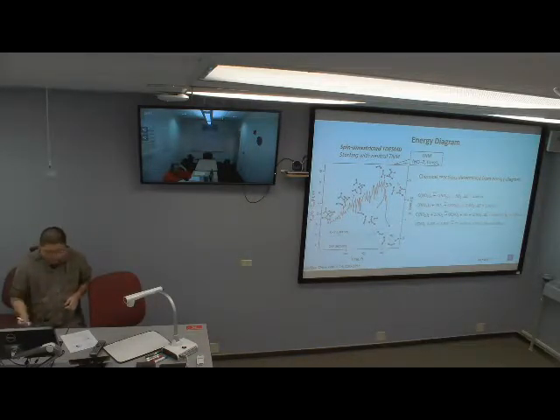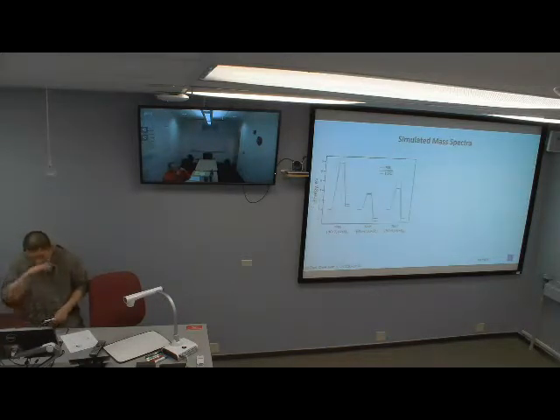Due to this isomerization, this species can lose nitrogen monoxide as well as carbon monoxide. So the final product consists of gas phase components. We have carbon monoxide, nitrogen monoxide, and three nitrogen dioxide. And also from the energy diagram, we can get activation energy for these reaction steps. Here I calculated the total energy of initial reactant, transition state as well as final product using different trajectories, using different functionals. And as is expected, the activation energy varies with the choice of functional.